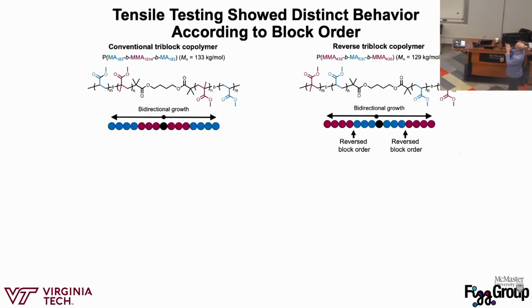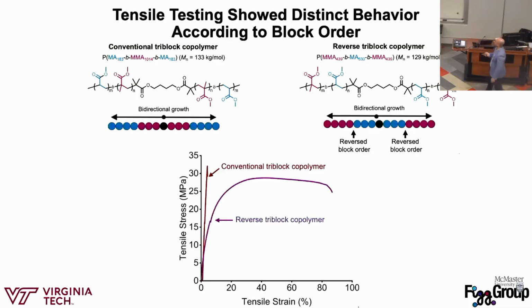So on this side, the methyl acrylates are on the inside, the methyl methacrylates are on the outside. Everything else looks the same. If you took an NMR, they'd look identical. We're just changing orientation. And so we did tensile testing. And so the conventional block copolymer is very brittle. So you can see it doesn't strain a lot. It breaks around 30 megapascals.